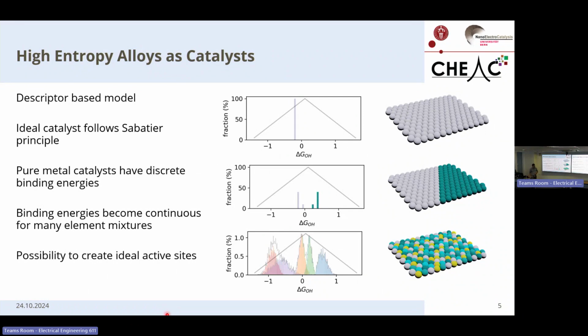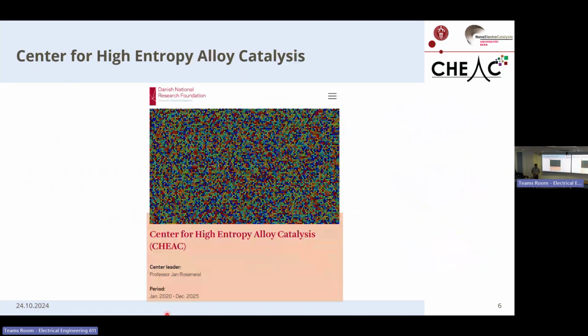And according to their work, if you create a high entropy alloy and you have a variety of different elements at the surface, the binding energies become a continuous function. So you can very precisely tune the binding energies of intermediates on your catalytic surface. And because you can very precisely tune them, it becomes possible to design active sites which have the optimal binding energy and will most efficiently catalyze a reaction. So this suggests that in the field of high entropy alloy catalysis, we can find novel catalysts that can rival the current industrial standards.